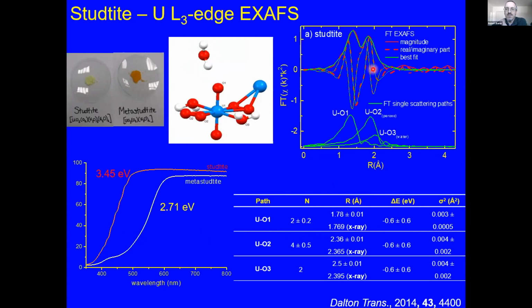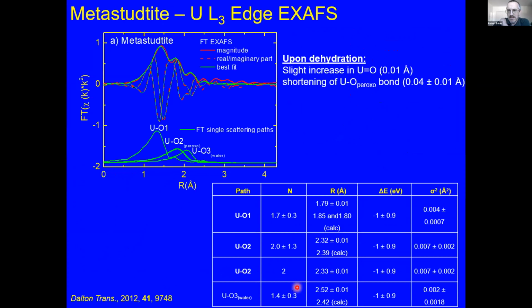These are the EXAFS studies from our synthetic studtite, and they match pretty well with the X-ray structures of the natural material. But metastudtite has never been structurally characterized. And what we see from our EXAFS is that there's a slight increase in the U-O bond length, which is about in line with the error of the measurements, but a distinct shortening of the U-O peroxy bond. So this was the first structural characterization of metastudtite.